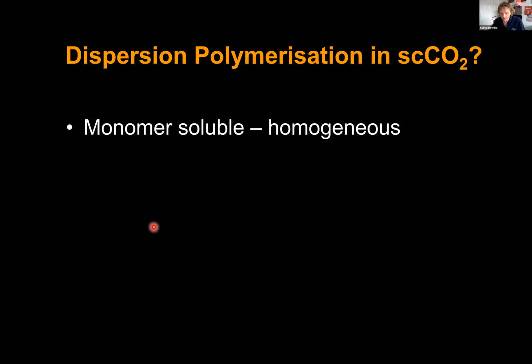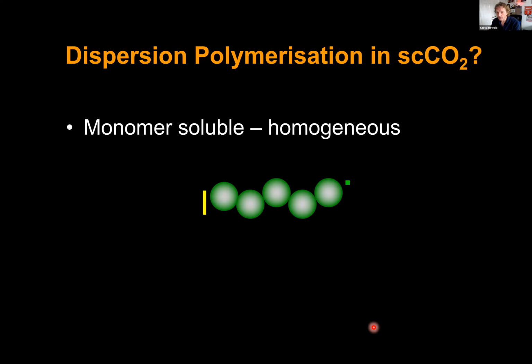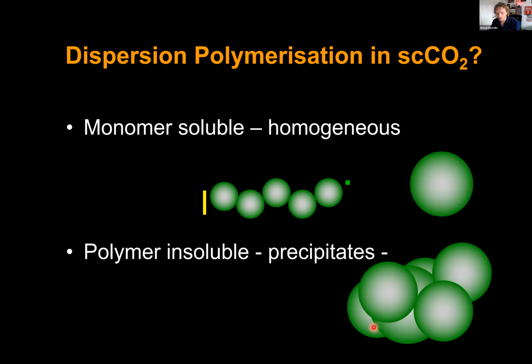So dispersion polymerization means that we take an initiator, usually an azo initiator. We can then create two radicals like so, and then the radicals will go off and start to initiate the monomer. And you get to a point where the polymer chain becomes long enough that it no longer dissolves. Under normal conditions, it just precipitates.